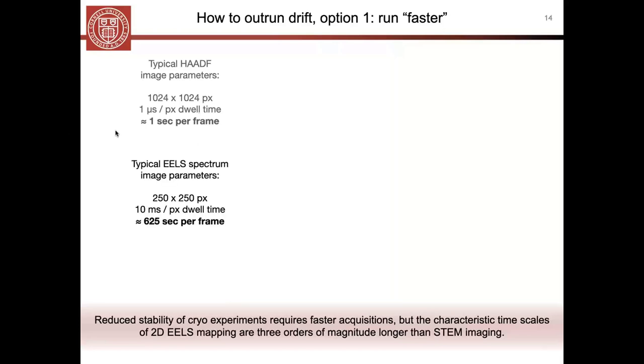And so if you compare that to your typical EELS spectrum image, a two-dimensional spectrum image, you do have to sacrifice a lot on the pixels, partly because of the experiment, but also partly just the practicality of the data. But you're going to bump up your dwell time to something like 10 milliseconds. So that's a much more standard EELS SI dwell time. And so this results in several minutes per single scan frame, right?